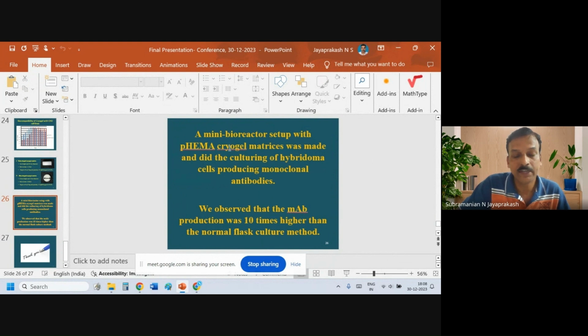And in fact, with this material, we have done a study. We developed a mini bioreactor setup with this cryogel matrix, and we did the culturing of hybridoma cells producing monoclonal antibodies. We observed that the monoclonal antibody production was 10 times higher than the normal static flask culture method.